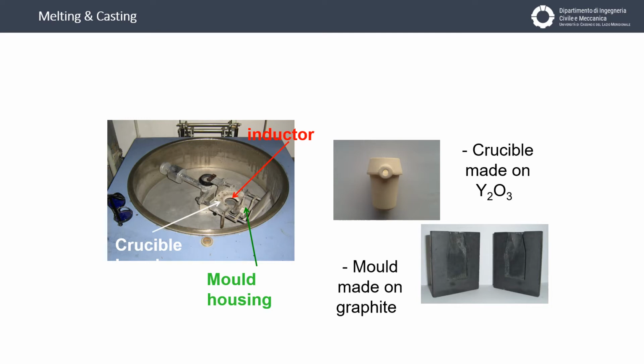has been to produce the material using a vacuum crucible posed in a furnace without air and using a noble gas like argon in order to eliminate oxygen inside. We use the crucible made of yttria because the yttria is very stable in terms of chemical action, and the casting has been in a mold made of graphite, as you can see in the slide.